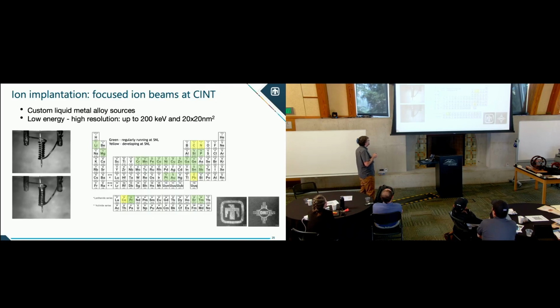These are custom focused ion beam tips, which is a sharp needle point in a reservoir, and this total scale is a couple millimeters. And then you actually dip it into a liquid metal alloy. So gallium is the most traditional FIB, because you can really melt it easily, apply a high electric field, and emit ions from this tip. All right, but at Sandia, we have a group that actually does this for a lot of different ions.